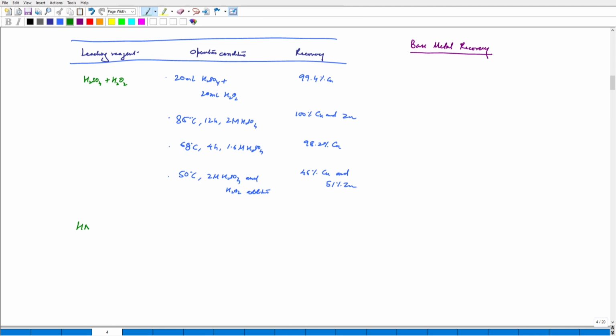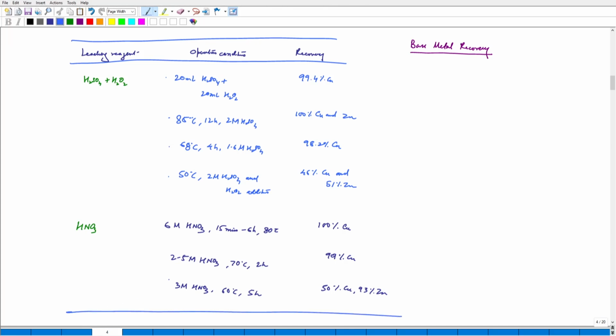We have, let's say, HNO3. So this was for H2SO4. Now if we write for HNO3, we have, let's say, 6 molar HNO3, 15 minutes. The reaction duration is 15 minutes to, let's say, 6 hours. And at 80 degrees Celsius, we can reach nearly up to 100% copper. 2 to 5 molar HNO3, 70 degrees Celsius, 2 hours, 99% copper. Let's say 3 molar HNO3, 60 degrees Celsius again, 5 hours, 50% copper, 93% zinc. This tells us that a wide variety of recoveries can be described.